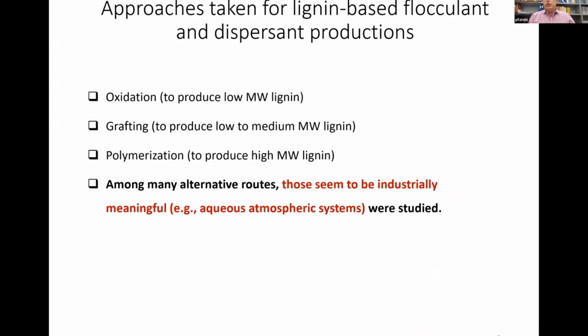So what I've been doing in the past 10 years, I focus on 3 different approaches to modify lignin. One was oxidation. Basically, if you oxidize lignin, you're going to add some carboxylic groups and maybe some other groups to lignin, depending on the reaction. You are going to open up the ring structure and cleave some of the covalent bonds. So we will have a little bit of molecular weight decrease and yield decrease. Oxidation usually is followed by a yield drop.